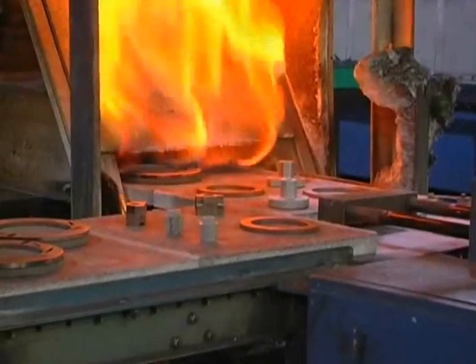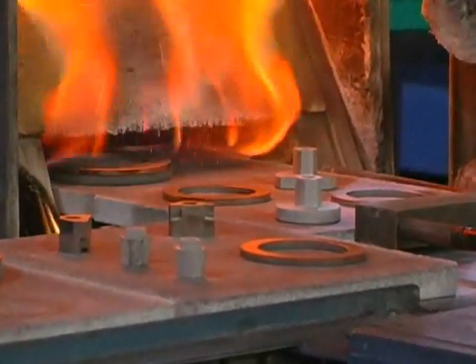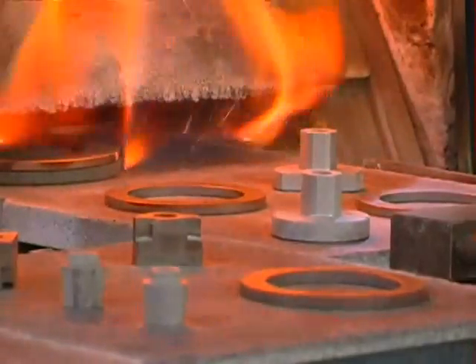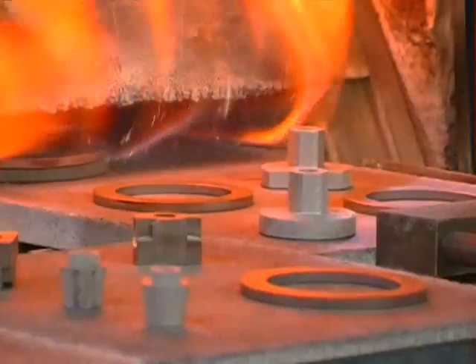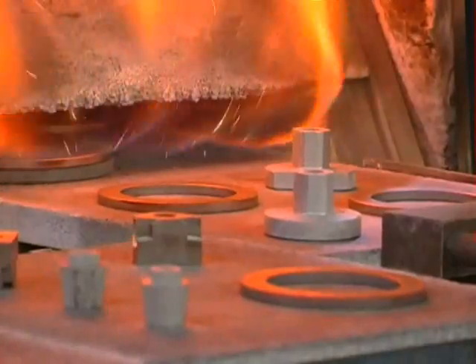Material selection is most often limited by the type of sintering furnaces that will be used in the processing. Sintering temperatures, both in the heating and cooling cycles, and the types of processing gases or furnace atmosphere will control the characteristics that are required of your product. At Phoenix, we have furnaces capable of sintering temperatures up to 2,400 degrees Fahrenheit or 1,315 degrees Celsius.